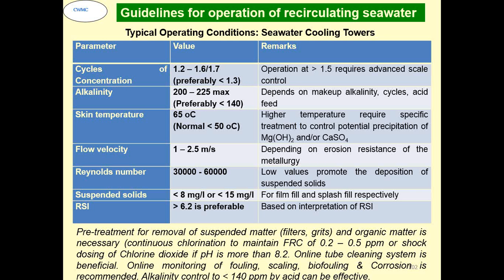Flow velocity not more than 2.5 meter per second. Of course, it will depend upon the erosion resistance of the tube metallurgy there. Something like titanium, it can go beyond 7 meter per second as an erosion resistance, but then it will cause some other problems also. Reynolds number not more than 60,000. Suspended solids less than 8 ppm for film type, or less than 15 ppm for splash type fills. RSI greater than 6.2 is preferable.